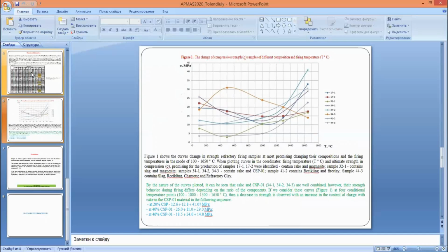By the nature of the curves plotted, it can be seen that the cake and the CSP-01 are well combined. However, their strength behavior during firing differs depending on the ratio of the components. If we consider these curves at 4 conditional temperature points, then a decrease in strength is observed with an increase in the content of charge with cake and CSP-01 material in the following sequence: at 20%, at 40%, and at 46%.